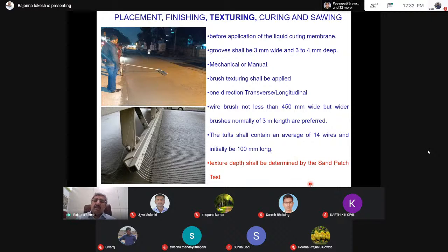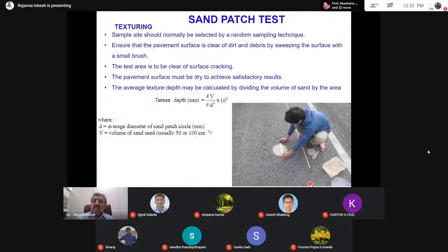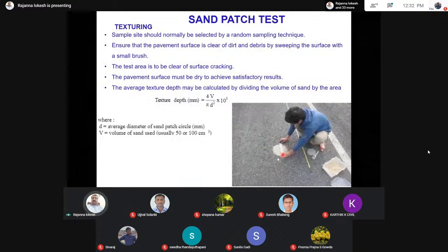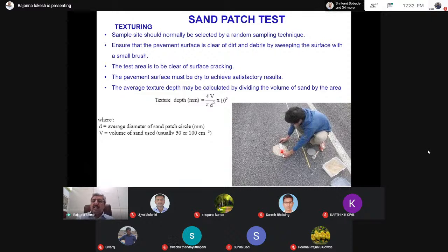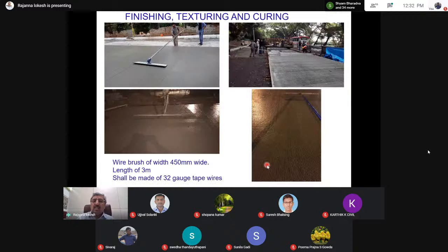The texture depth can be measured using a method called the sand patch method. So this is a sand patch method to know the texture. You identify a known section in the site, clean all the dirt, take a suitable volume of fine sand, and then spread it across the designated area. The quantity of sand utilized relative to the area spread will give us the texture depth. So these are some of the photographs with texturing.